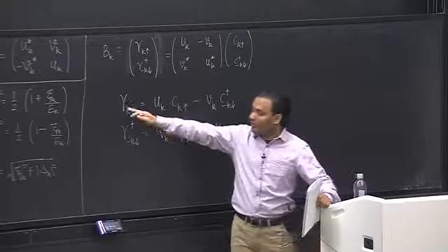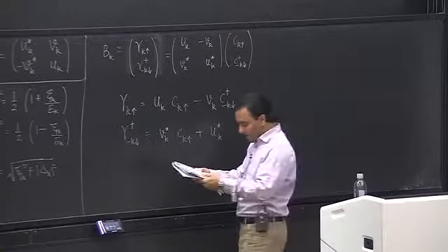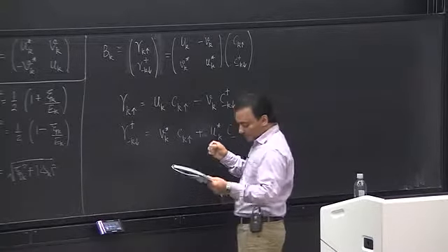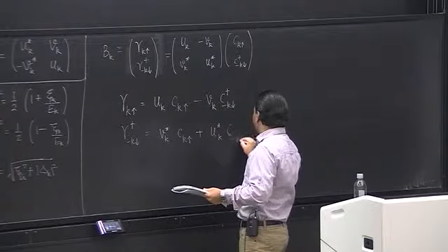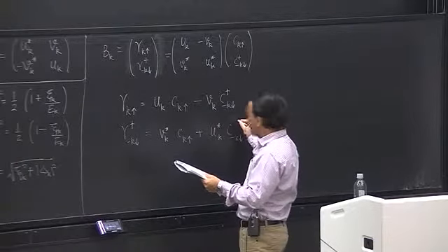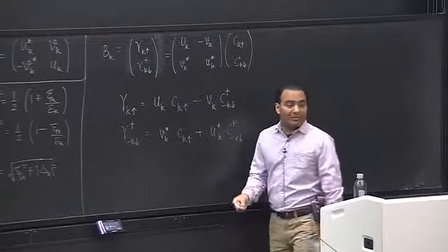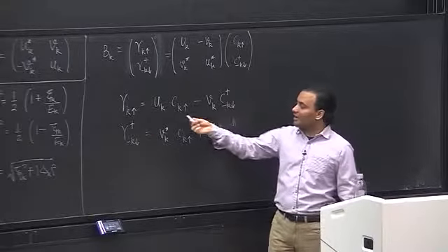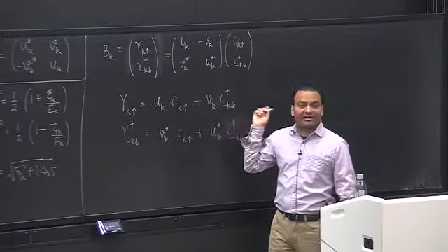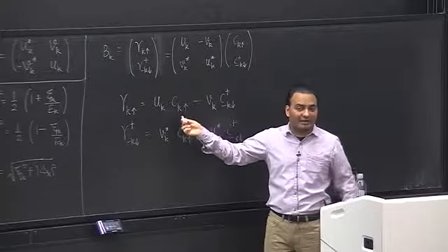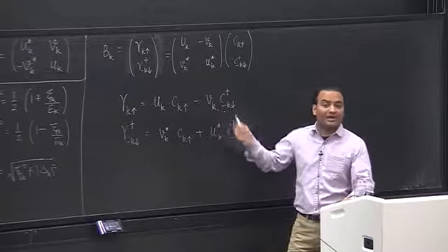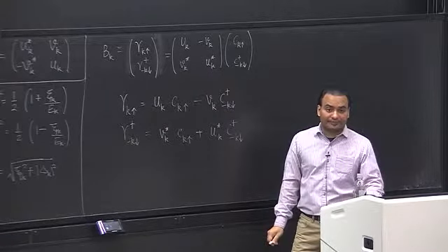So we have new operators, gamma K up and gamma minus K down. And in terms of these new operators, the Hamiltonian is diagonal. So we have the eigenstates, but these new operators are really superposition of electronic creation and annihilation operators, and they have these coherence factors, UK and VK, in them.